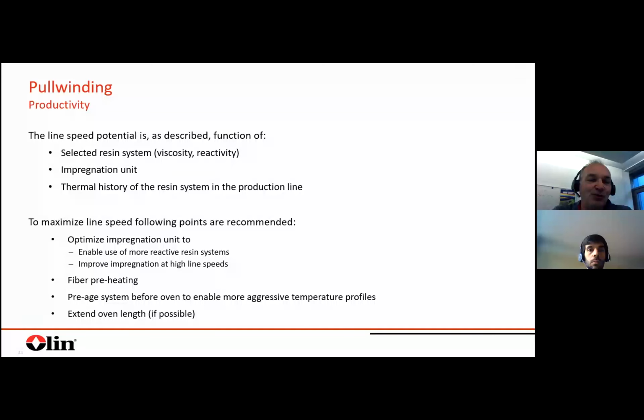In best case, really to enable the use of more reactive resin systems. So you, for example, in a simple way, create a bath where you don't require the pot life of several hours. Maybe 1 hour is sufficient. Then you for sure can accelerate the system much more. Also a way to improve the impregnation at high line speeds is by changing the tensioning, guiding of fibers or whatever. Fiber preheating is quite efficient in terms of impregnation.